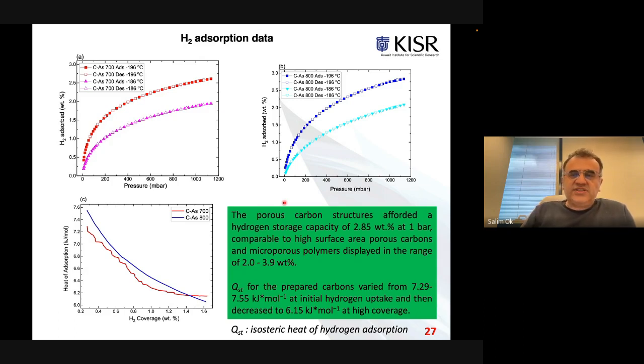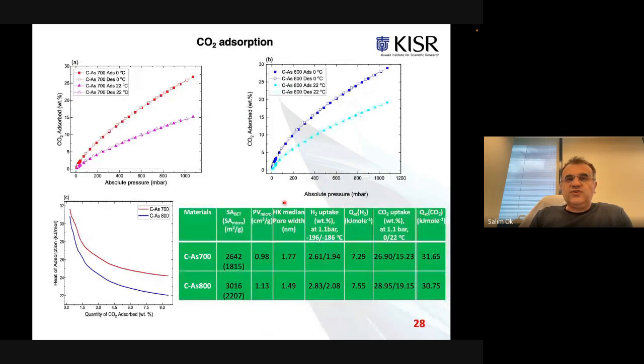We recognized that the porous carbon structures show hydrogen storage capacity of 2.85 weight percent at 1 bar. Besides that, we also looked at the isosteric heat of hydrogen adsorption, ranging from 7.29 to 7.55 kilojoule per mole. There was a slight decrease at high coverage, but on the other hand, we also focused on carbon dioxide adsorption.